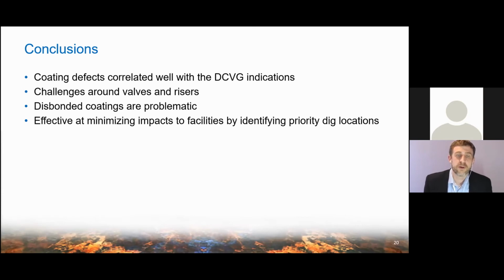And in conclusion, I'd say that the coating defects have correlated pretty well with the DCVG indications. So overall, the program has allowed the facilities to gain a lot of confidence, in terms of, do we have a problem in our facilities? Can we effectively isolate it with these techniques? And there were a lot of digs that went into gaining that confidence. Now, there definitely are challenges around valves and risers. They complicate things and they need to be accounted for carefully. And you won't have the same degree of confidence sometimes that you would have on a simple survey on a cross-country pipeline.